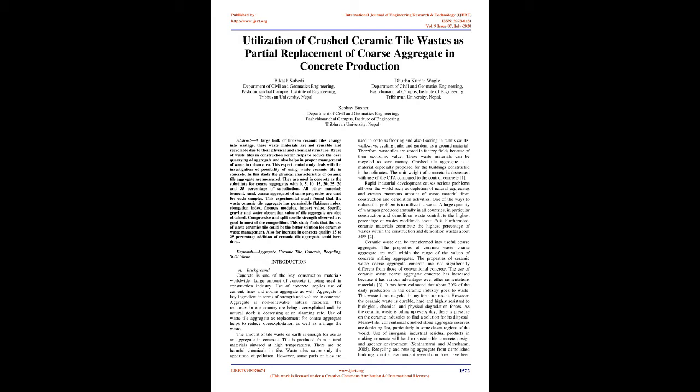This experimental study found that the waste ceramic tile aggregate has permissible flakiness index, elongation index, fineness modulus, and impact value. Specific gravity and water absorption value of tile aggregate are also obtained. Compressive and split tensile strength observed are good in most of the compositions.